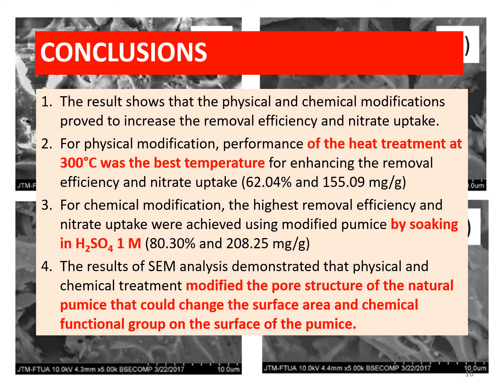Finally, I want to explain to you the conclusion. The results show that physical and chemical modification proved to increase the removal efficiency and nitrate uptake. For physical modification, the heat treatment at 300 degrees Celsius was the best temperature for enhancing the removal efficiency and nitrate uptake. For chemical modification, the highest removal efficiency and nitrate uptake were achieved by using the modified pumice by soaking in sulfuric acid.